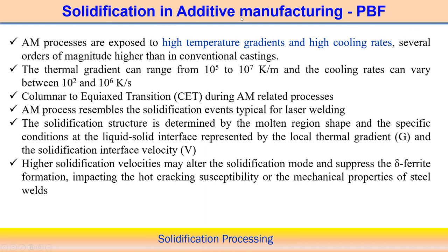The thermal gradient ranges from 10⁵ to 10⁷ K/m, and the cooling rate can be 10² to 10⁶ K/s. These are rough estimates; the actual values vary depending on the specific technique and associated process parameters.